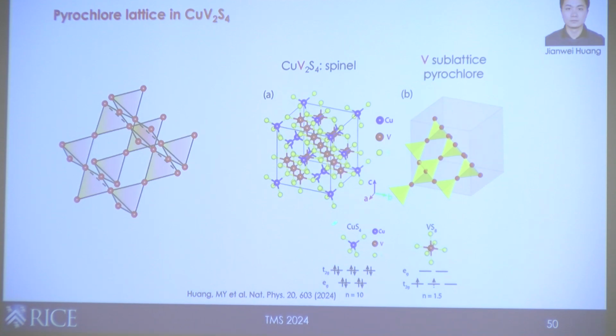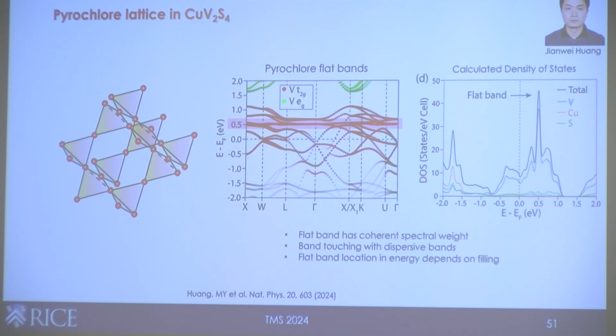We figured out that if you look at the chemical environment of these different things, the copper tetrahedron is actually fully filled. And then it's the vanadium, which is partially filled in the T2G orbitals. So this suggests that this could be very promising because the copper and the sulfur states may be farther away from the Fermi level, leaving behind the low energy electronic structure dominated by the vanadium sublattice. So this is something that's worth looking into. You can see that in the DFT already.